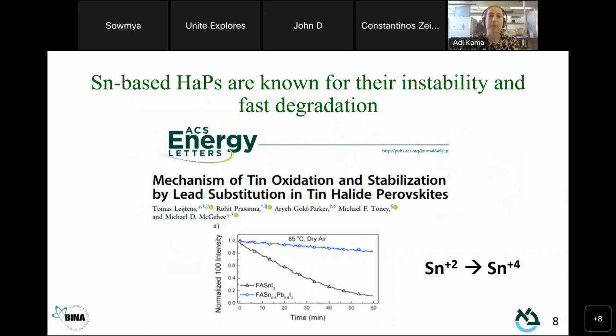So a little bit about the tin-based halide perovskite. They have a very small band gap, which is very suitable for solar cells, yet they're not stable. Tin +2 is not stable in the +2 oxidation state and tends to oxidize to the +4 oxidation state, causing fast degradation of the material and, of course, the solar cell performance, as we can see in this paper.